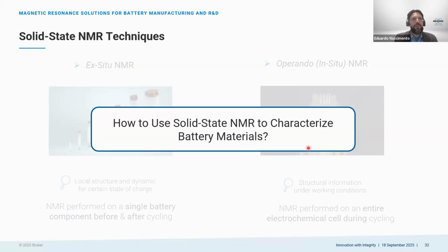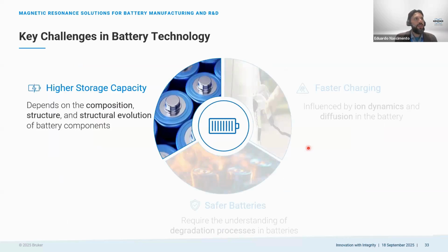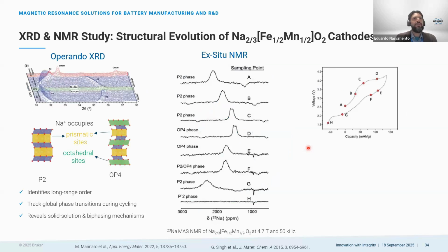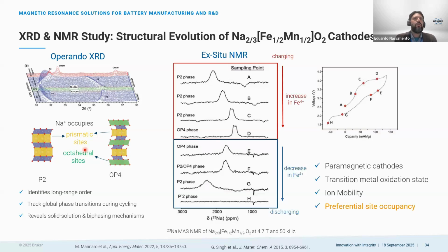So how can we use solid-state NMR to characterize battery materials? We are going to start talking a little bit about higher storage capacity. Here we have a nice example where XRD and NMR were applied to study the structural evolution of sodium in a cathode material. With XRD, you can identify the long range order and even track the global phase transition during cycling. And with NMR, we can talk about the preferential site occupancy. In this study specifically, the authors were able to see that in the higher state of charge, the sodium was preferably sitting on the octahedral sites of the OP4 phase. And more than that, after discharging, this process was reversible, with the sodium coming back to the P2 phase.